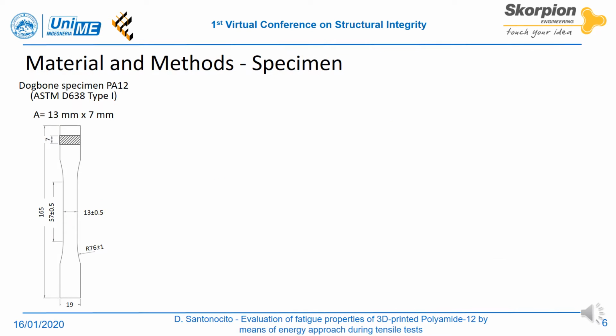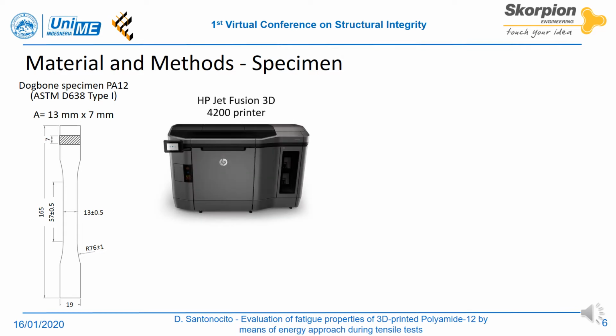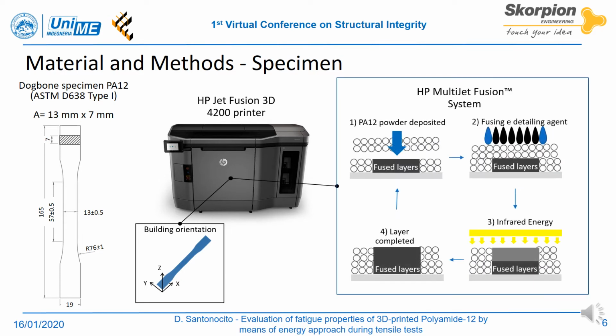Static tensile tests were performed on specimens made of 3D-printed Polyamide-12 according to the geometry prescribed by the ASTM D638 standard, with a nominal cross-section of 13 per 7 mm. The specimens were realized with an HP Jet Fusion 3D printer along the XY plane, adopting the polymeric powder HP 3D High Reusability PA12. The printer adopts the multi-jet fusion printing system. It is a powder-based technology without the adoption of a laser source. The powder bed is preheated uniformly, and a first layer of liquid fusion agent is deposited on the printing plane. Later, a second layer with detailing agent is deposited in the points where the material needs to be melted.